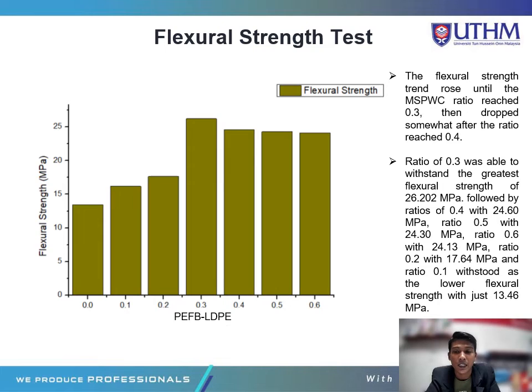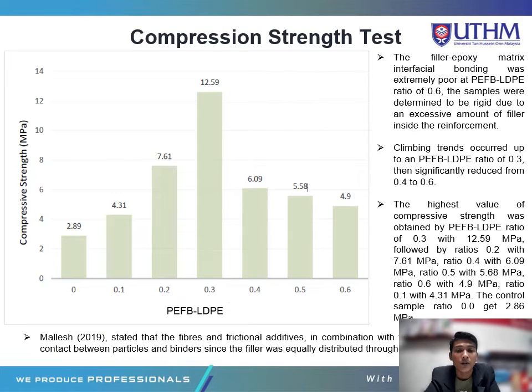Ratio 0.1 withstood the lowest flexural strength with just 13.46 MPa. For the compression strength test, the filler epoxy matrix interfacial bonding was extremely poor at PEFB ratio 0.6. The samples were determined to be rigid due to an excessive amount of filler inside the reinforcement. Climbing trends occurred up to a PEFB ratio of 0.3, then significantly reduced from 0.4 to 0.6.